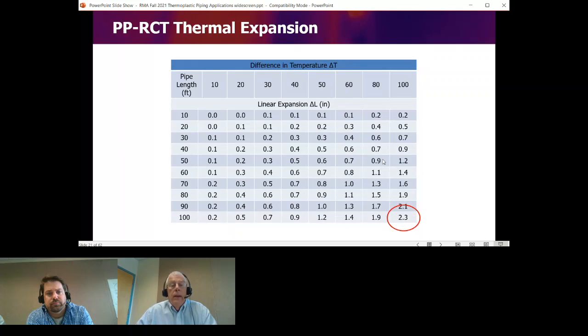Just for comparison, here's a table from some PPRCT piping. The left column is basically delta T from your installation temperature. So, for example, if you install on a cold water system or a domestic hot water system at maybe 60 degrees, and you're adding your 50 or 60 degrees, you're getting up with a delta T of 100. If you use PPRCT piping, for every 100 feet of piping, you're still growing 2.3 inches. That's not as much as copper or steel, but standard uniform PPR piping is probably double that at least, or even higher in some cases, which makes it harder to control linear expansion.